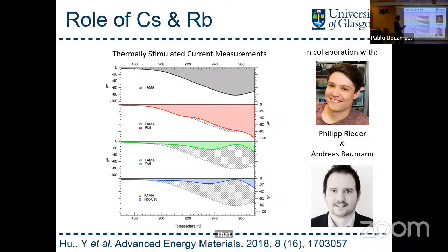So anything that comes out really early in the process is a very shallow trap. Anything that comes out later is a deep trap. So the starting material has a lot of deep traps. When you add rubidium, you're not really changing that. This is not significantly different. When you add cesium, see that we've completely removed the majority of the deep traps.